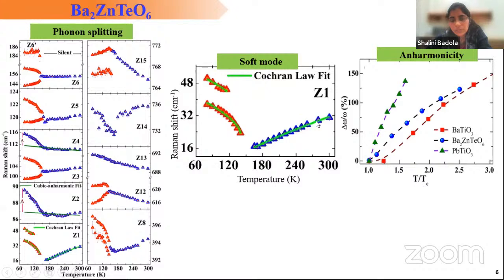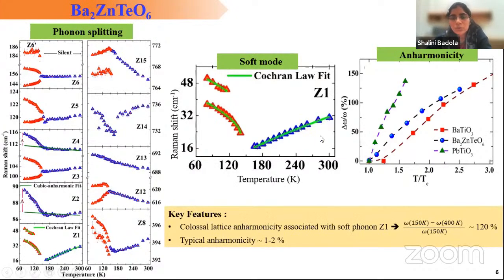An interesting point to note here is that the overall change in frequency of this mode in the high temperature phase, that is trigonal phase, as well as in the low temperature phase is really large. It is around 120% in the high temperature phase, which is significantly high as compared to commonly encountered anharmonicity of 1.1 to 2%. In the low temperature phase, it is around 94%. So from this, we can say that the enormous anharmonicity associated with this soft mode can play a very important role in driving the phase transition in BZT.